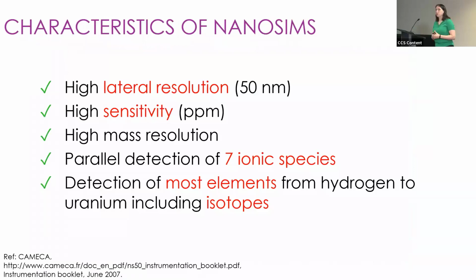So why might you want to use NanoSIMS? For various different applications, and also specifically looking for hydrogen in metals. The NanoSIMS offers high lateral resolution. We can actually focus that primary ion beam down to 50 nanometers, although routinely, due to trade-offs between lateral resolution and sensitivity, we may be looking at somewhere between 100 and 200 nanometer spatial resolution. That's much better spatial resolution for chemical mapping than you can get, say, in an SEM with EDX. The NanoSIMS can offer high sensitivity, so we can look at trace element distributions. We can look at parts per million level concentrations for some elements. So again, much better than SEM and EDX.